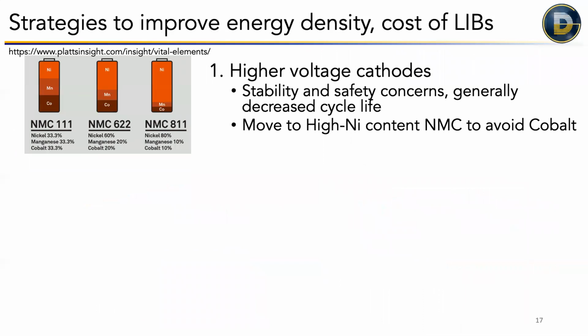So then there's still a lot of work being done on the lithium-ion batteries, whether it's changing to different cathodes. The big push here is to move away from cobalt-based batteries, because Congo produces almost 20 times more cobalt than any other country in the world, and it produces over 70% of the cobalt that is produced in the world. So it has a lot of social implications to have a lot of cobalt in batteries. So we're really trying to move away. And in the past 5 to 10 years, we've gone from a 1-to-1-to-1 ratio of cobalt in this most common cathode called NMC to now 8-to-1-to-1. So we've dramatically reduced the amount of cobalt, which is really good.